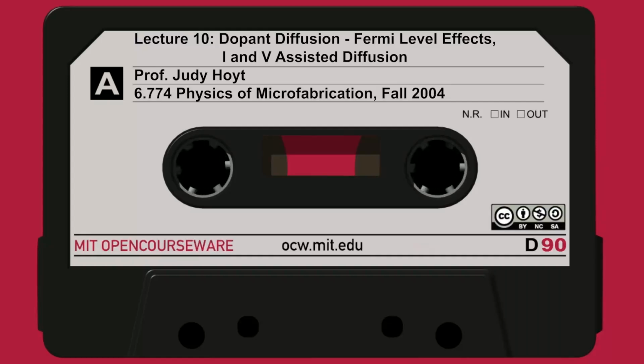So if you just look at this flux equation for a moment, what is it saying? Well, it says if, let's say H is some reasonable value, if Ca is much, much different, then Cb over K0, this difference is going to be a large number. There's going to be a big flux. So it's going to allow flux to flow basically until Ca approaches Cb over K0, and then the flux goes to 0. So it's going to force the concentration profile across that interface to have a ratio that's equal to K0.